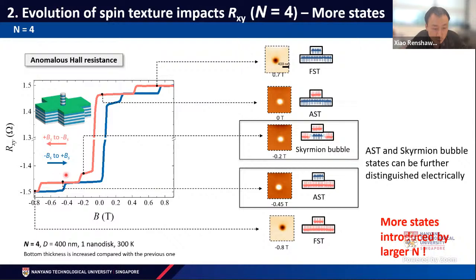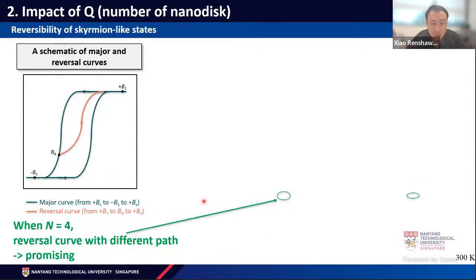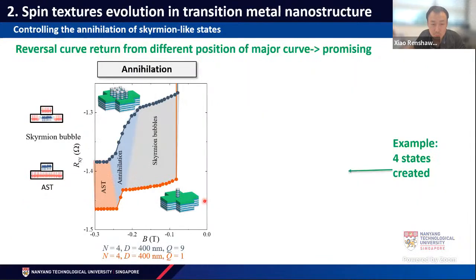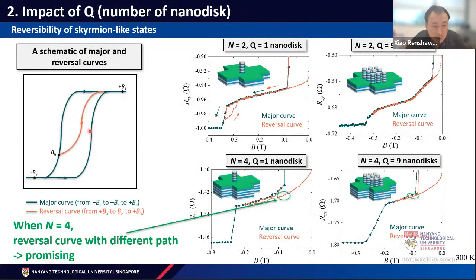For us, the more interesting one is here, this region, which is a skyrmion bubble region or skyrmion-like magnetic state region. So we want to see if we play with the magnetic field here, what we will get, so how we can generate some multi-state here. What we did was just sweeping the magnetic field from a particular position and then going backward, right? So for example, we do the major curve or the green curve and stop, for example, here. We go back along the orange curve. We see whether we can get back to 0 and whether we get some non-volatile states.